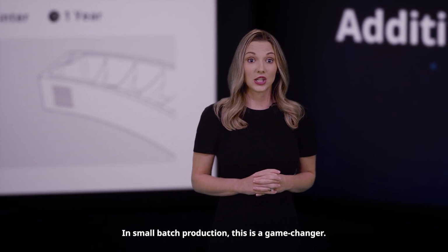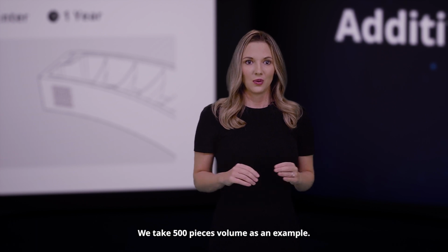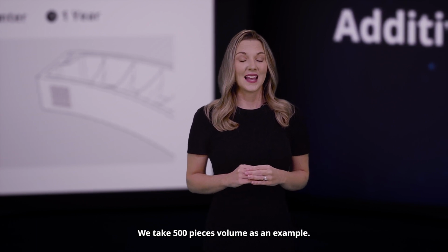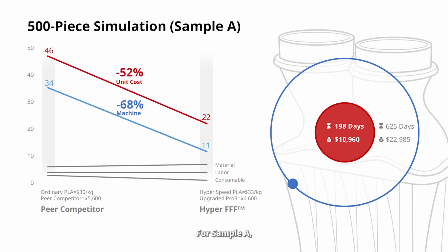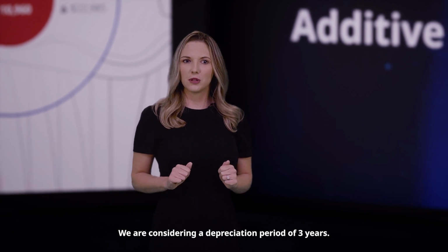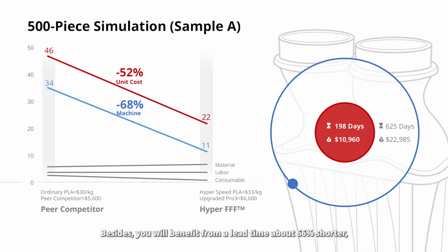In small batch production, this is a game changer. We take 500 pieces volume as an example. For sample A, a unit cost shrinks from about $46 to around $22, which is roughly a 52% drop. The major improvement comes from the lower machine depreciation cost allocated to each printed part, which is reduced from around $34 to around $11. We are considering a depreciation period of 3 years.